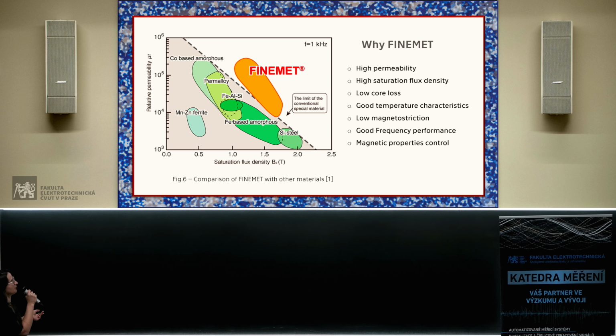The best thing about this type of material is that we can process the master alloy in a certain way to get a certain state, with different sizes of domains or a different ratio between amorphous state and crystalline state. And after a certain processing, we will get properties of this material which could be better than other types of alloys in terms of using it in fluxgate sensors.